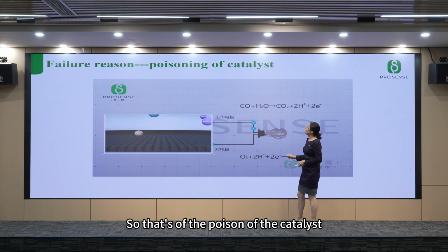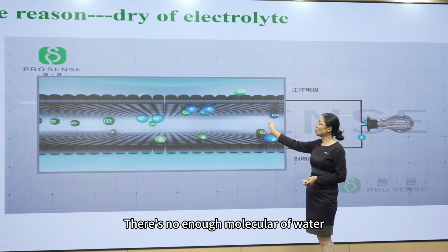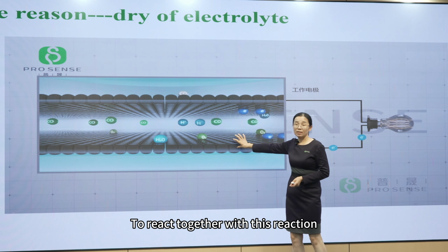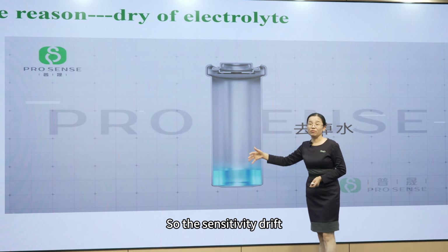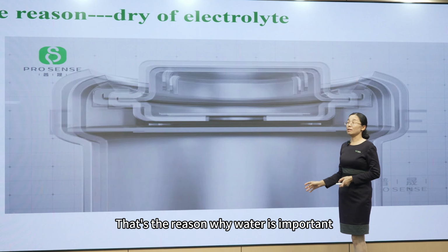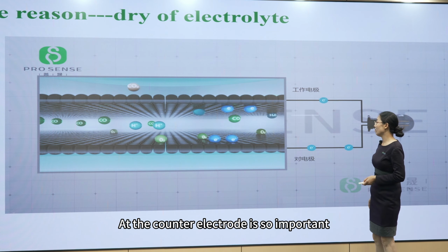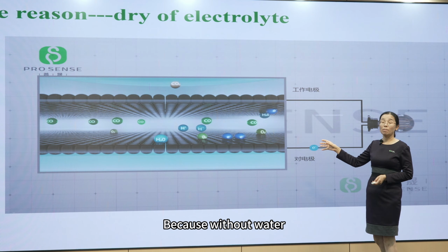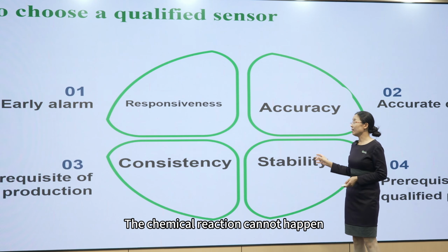And for the drying of the electrolyte, if there's no water inside, there's also no water from the outside. There's no water in the water tank, and the humidity is very low. There's no water to compensate for the reaction, and when carbon monoxide comes here, there are not enough water molecules to react, so the sensitivity drifts. That's why water is important, and why the recycle of the water generated at the counter electrode is so important, because without water, the chemical reaction cannot happen.